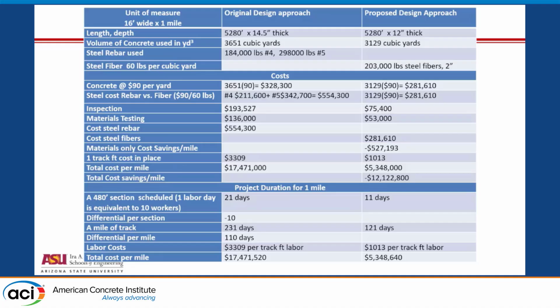However, that amount of steel was replaced with almost 50%. So instead of almost 480,000 pounds, we went to 200,000 pounds of steel fiber. So more than twice reduction in the total steel. The cost of concrete was slightly lower, so 328,000 versus 281. That's because of 2-inch savings. The fact that we removed the cover itself is sufficient if we do any project with fibers, if you don't have rebar. So the added cover that we assume that it cracks, it's tremendous.